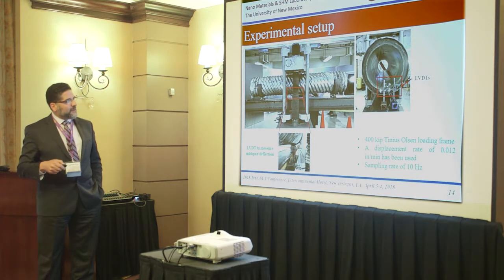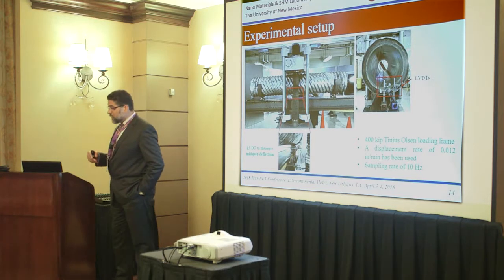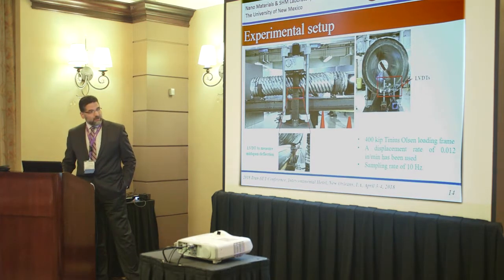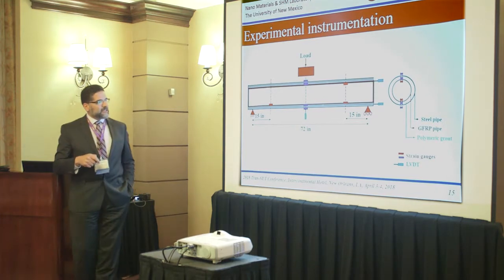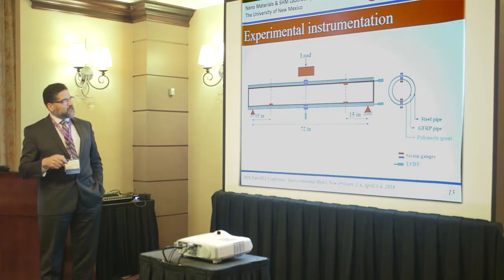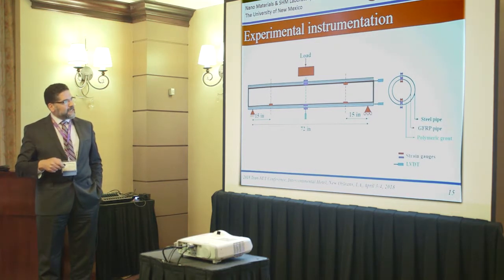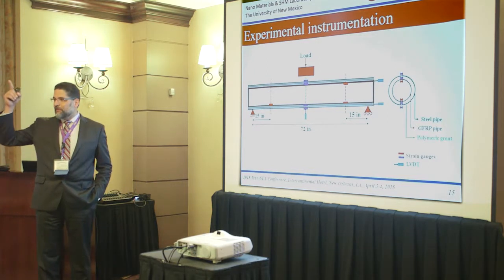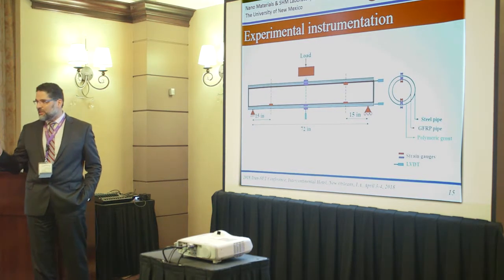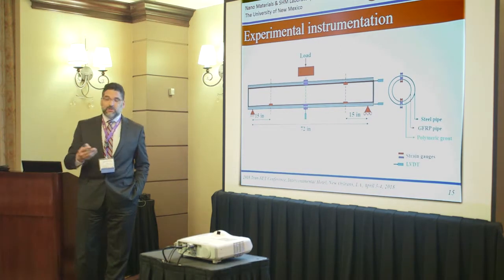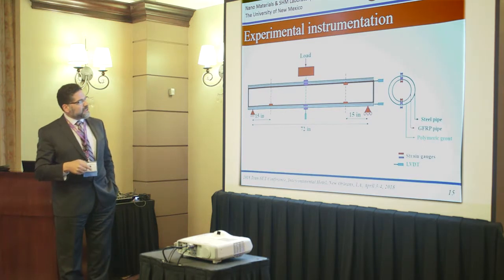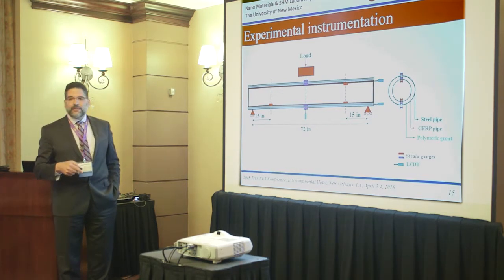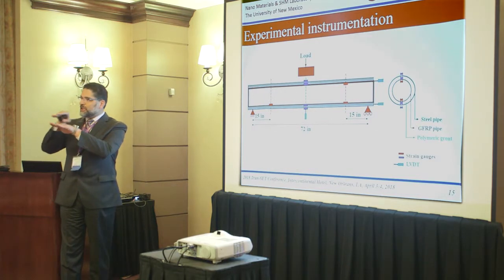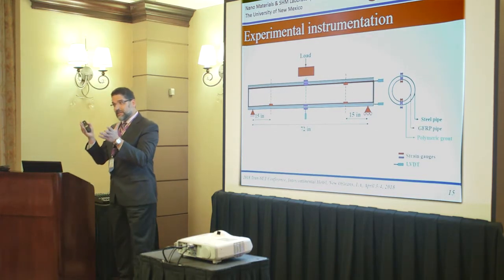We used different LVDTs and strain gauges to make sure that we are measuring the composite action. This schematic shows the LVDTs and the strain gauges. We put strain gauges on the glass fiber, inside and outside of the glass fiber, and strain gauges on the steel. Our objective is to make sure that the flexural profile is achieved, and that the glass fiber is carrying the load as we are doing the testing. We use LVDTs to get the displacement. We also use LVDTs at the end to check if there is any horizontal longitudinal shear movement, if there is a slip that's going to happen.